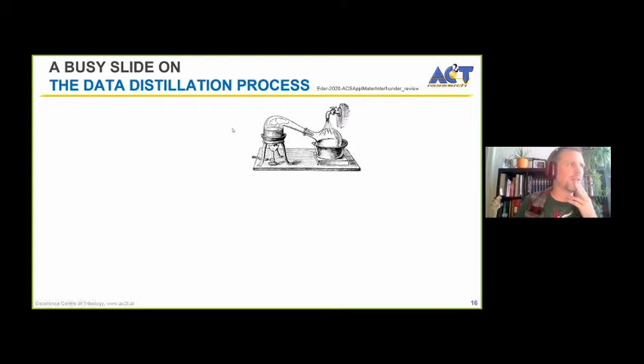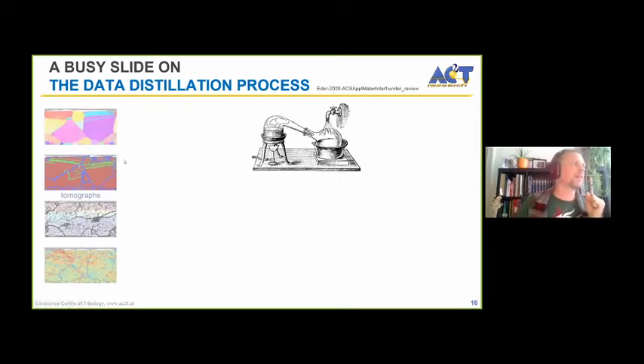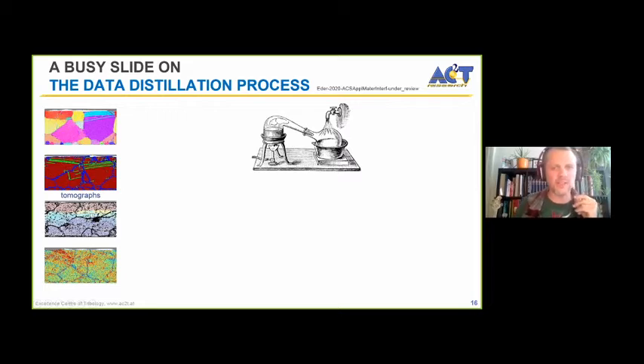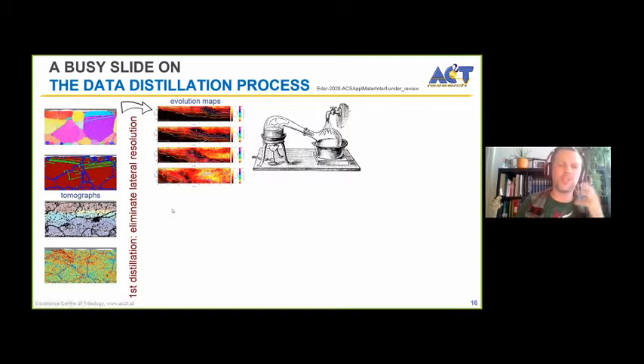And usually, explaining all of this takes about half an hour. So I'm going to give you the 1.5 minute summary. So we start out, when we look at all of our simulation runs in the end, we look at EBSD visualizations, we look at grain boundary and twins and stacking fault visualizations, we look at atomic advection velocity visualizations where we see the shear layer evolving, and we look at the stress visualizations. And then we start to distill it.